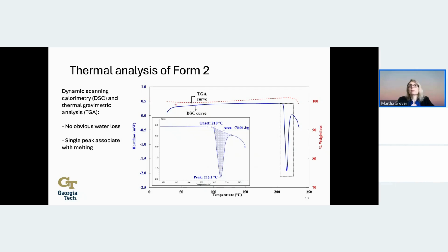With the DSC curve, similarly, we were not able to see clear peaks other than the melting peak. And that's at a similar temperature to what we saw when we performed the thermal analysis on form 1, just above 200 degrees. And we were able also to quantitate the heat of fusion here and got a somewhat different, maybe 10% different, measured heat of fusion compared to the thermal analysis that we performed on form 1. Presumably this peak there was for form 1A melting. So that's thermal analysis of form 2.